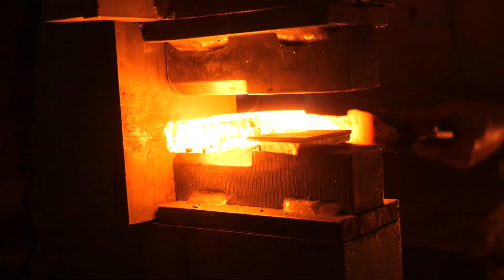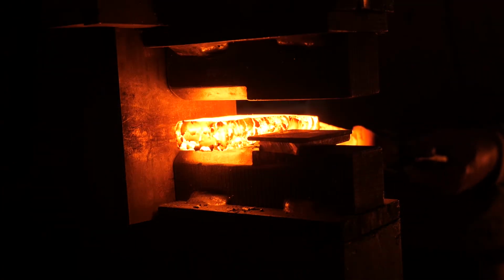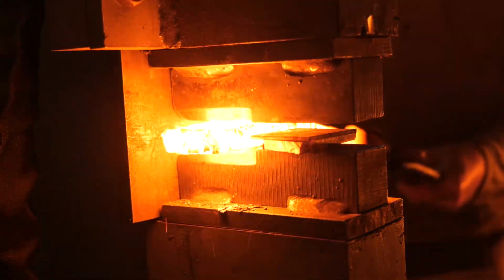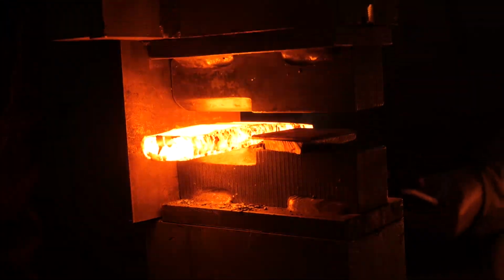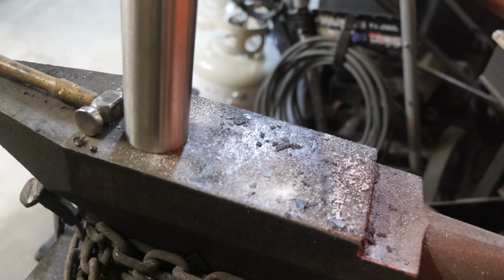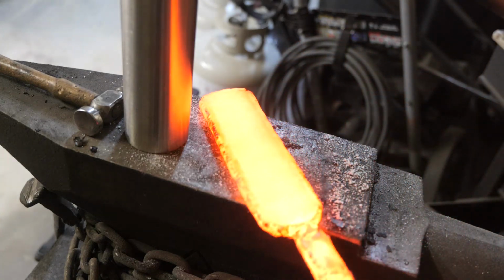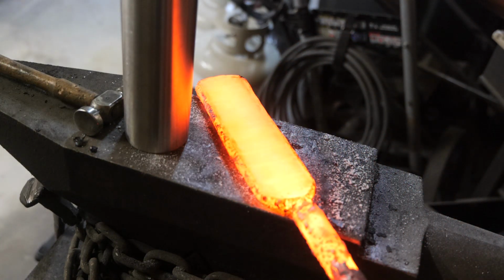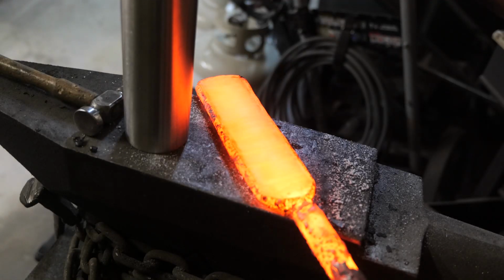The billet was held at forge welding temperatures for about 15 minutes in the forge before taking it to the press and flattening it out. I'm not going crazy with the first press. You guys probably noticed it was only squished a small amount before going back in the forge for another solid 10 minutes at forge welding temperatures, and then I finished the flattening.